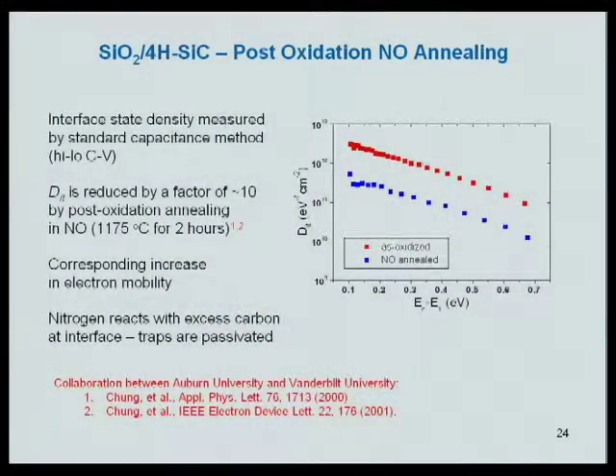Now, when we do electrical measurements, what we find is that there's a very high density of interface states. We're looking for interface states that are close to the conduction band that reduce the mobility of electrons in the conduction band at that interface. This is a log scale here, so we have an exponentially decreasing interface state density as the energy goes from zero, the energy of the conduction band, deeper into the gap. It's this very high density of interface states that we want to understand and try to get rid of, or at least get rid of their effects.